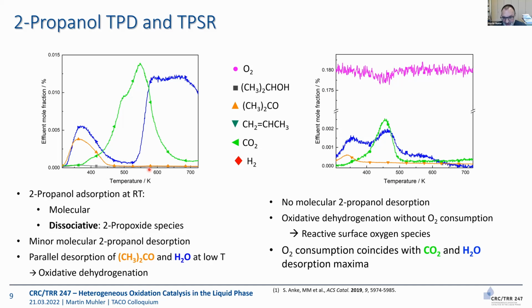You can make the experiment a bit more complicated. You adsorb 2-propanol, and then that is called temperature-programmed surface reaction. Then you heat up in oxygen, and that allows you to monitor the consumption of oxygen from the gas phase. You start again with seeing acetone and water in the beginning, but then when we also detect oxygen uptake, then we see CO2 and water formation.